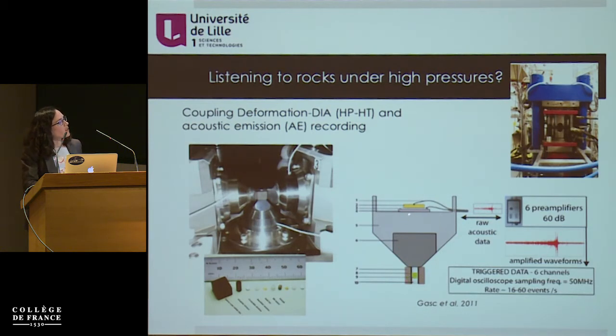And this transducer transforms the elastic wave that comes from the sample into an electrical signal that is amplified and recorded. What is not shown here is there is also a continuous recording possibility on this setup, and this allows you to have a kind of catalog of your acoustic emission events, and therefore to have statistics that are not biased by some recording in the dead time in the system.